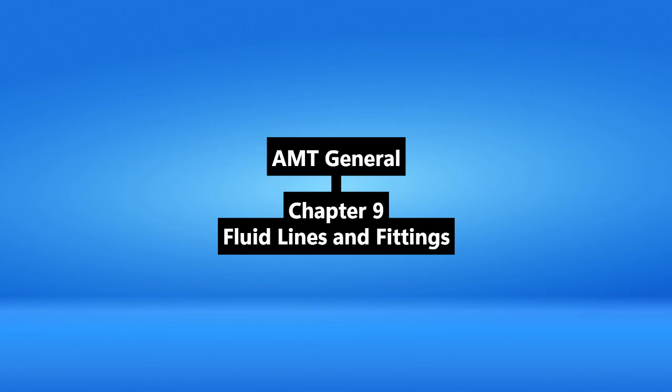Critically important. They mention knives, the cutter's deburring edge, or special tools like in Figure 9-3. But the big warning is, don't reduce the wall thickness doing it. Because that creates a weak spot. Precisely. Could lead to cracked flares, failures under pressure. Oh, and a useful tip they mention: clamp small tubing in a flaring tool held in a vise for easier cutting. Clever. Okay, on to bending.